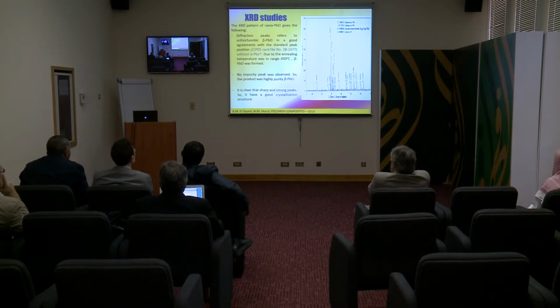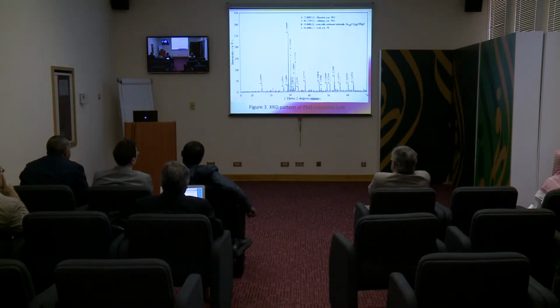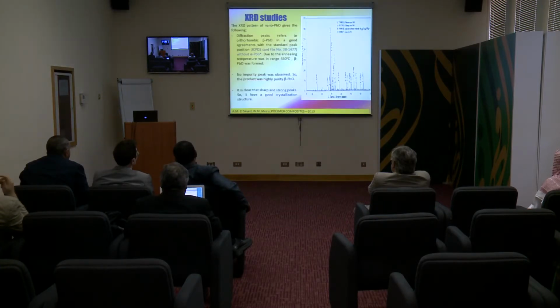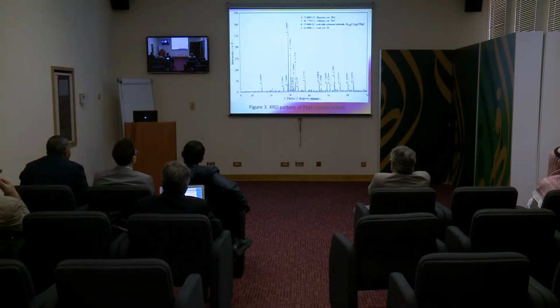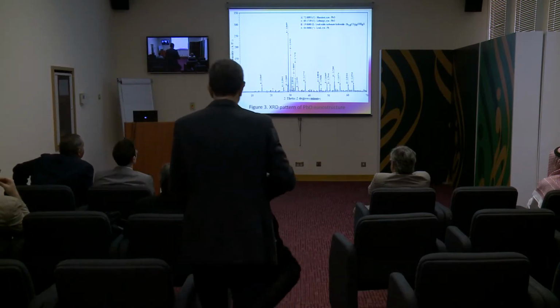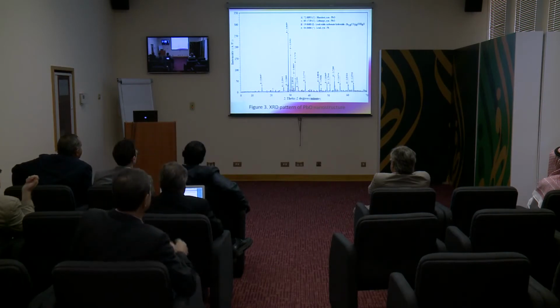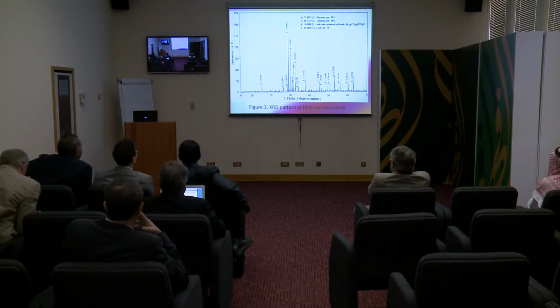XRD study. It is clear from the XRD pattern that it is pure beta lead oxide. Diffraction peaks refer to orthorhombic beta lead oxide, in good agreement with the standard peak positions, due to the annealing temperature being in the range of 450 degrees centigrade. Also, there are no impurities. You can see only sharp peaks, and in the background there are many indications that there are no impurities.